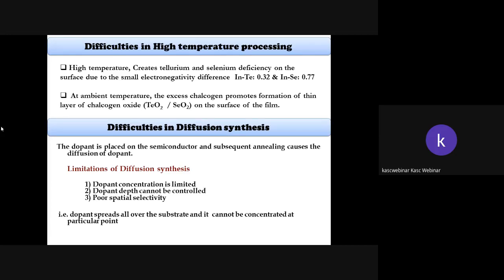Further, the difficulty faced in high temperature processing, while choosing this kind of a chalcogenide material: if you process further at a higher temperature to prepare a single phased sample, then it creates a tellurium or selenium vacancy on the surface due to a very, very small electronegativity difference between the involved metal and chalcogenide. For example, I have chosen indium metal as a low melting point material as a choice. So indium and tellurium have an electronegativity difference of only 0.32 Pauling. And in the second case, in indium selenide, it's only 0.77 Pauling. Actually, this very small electronegativity difference ends up with different polymorphism in a sample.